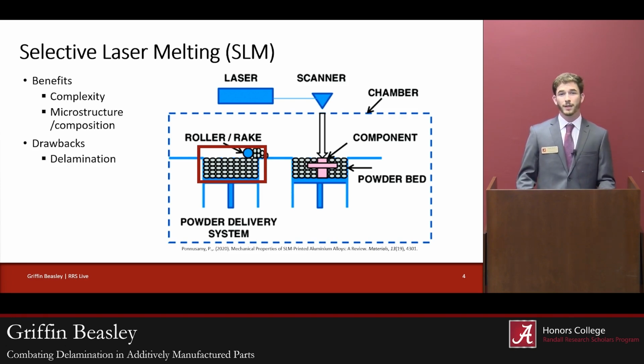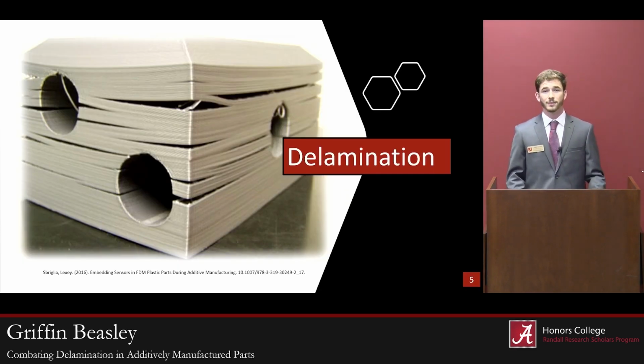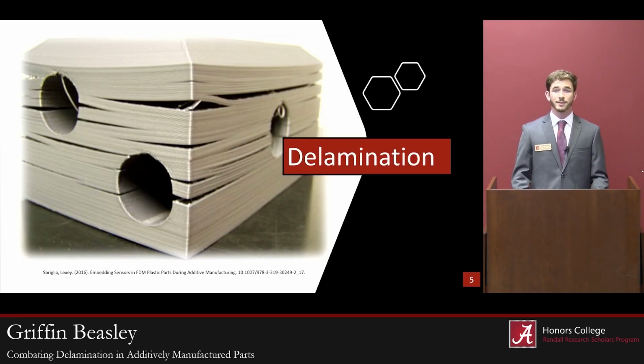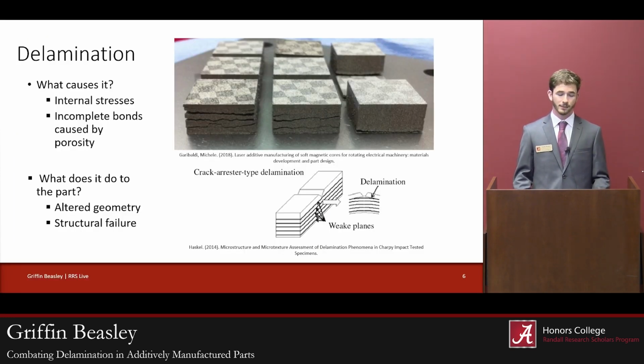However, there is one major drawback to selective laser melting and additive manufacturing as a whole, and that is something called delamination. Delamination is the separation of layers in an additively manufactured part. As pictured in the slide, the bonds between the layers break and the layers begin to pull apart from each other. Now, this is typically caused by two main things, and those are internal stresses during the creation process and incomplete bonds caused by porosity.